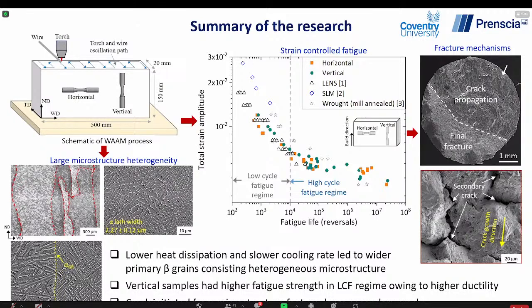And when we looked in detail at the crack propagation region, we found large secondary cracks, which is a consequence of the colony microstructure that we have observed, because that will lead to formation of secondary cracks, and also change the mode 1 driving force to sometimes mixed mode 1 and mode 2, and also help in lowering the overall crack propagation rate and increasing the overall fatigue life.